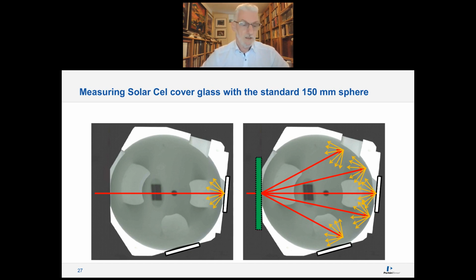That target is supposed to have the same properties as the rest of the sphere. It's the same material, but usually it's differently aged, so it does not really have the same value. For specular samples, like glass samples and thicker samples, which are not diffusive, that's no problem with reflection measurement. Even with normal reflection measurements, that's not really a problem.